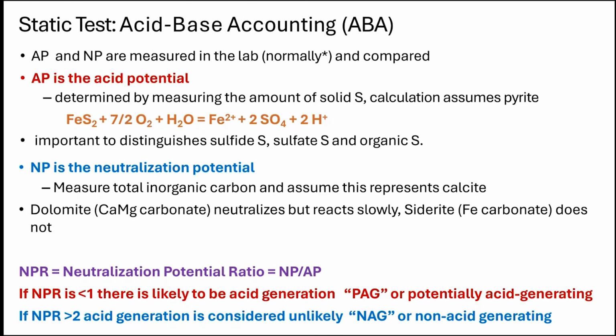And then they're compared. NP over AP is the neutralization potential ratio. And if it's less than 1, obviously you have too much sulfide, too much acid potential, and those materials are labeled PAG, or potentially acid generating. And if it's greater than 2, then acid generation is considered unlikely, and those materials are labeled as NAG, or non-acid generating. And between 1 and 2, it's ambiguous or indeterminate. You don't know which way they're going to go. So this is a very common tool. It doesn't tell us anything about rates or time, but it's a very common tool to characterize materials.